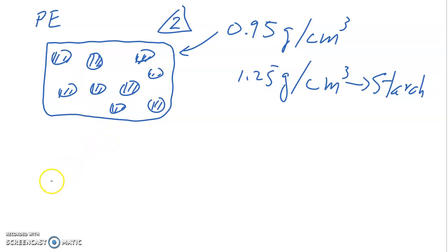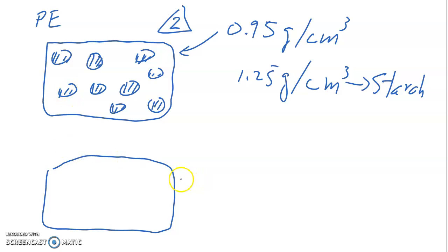Now, the student will start an experiment. He did it the same way as the previous experiment. The first thing is to melt the plastic, melt the polyethylene. The melting point of polyethylene is about 120 degrees Celsius. In order to make it flowable, the processing temperature needs to go a little bit higher. It needs to go to 140 degrees Celsius.